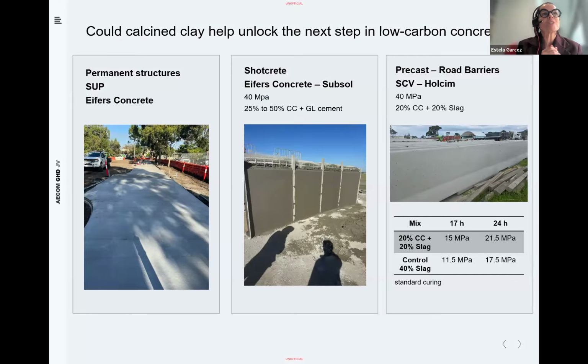Some of the recent ones that Miles and I have been involved in is this shotcrete trial. We all know that shotcrete is a very difficult, hard to crack application, and we have been seeing this application up to 50% cement replacement with calcined clay and GL cement, actually. And the shotcrete had no issues, we were very happy with the outcome of this, and it was the first trial. Everything already went spot on.